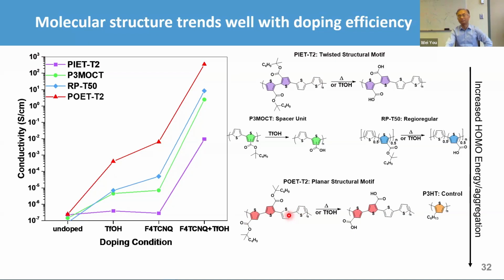But the true magic happens with the so-called POET-T2, because of the planar structure, and your mobility will be very high. And because of this interesting doping, you have a higher carrier density, and you end up with a very high conductivity, up to 500 in some cases. That's what I meant: even though you can have a thermocleavable side chain, depending upon how you remove them and how you process them, you will end up with different behavior.